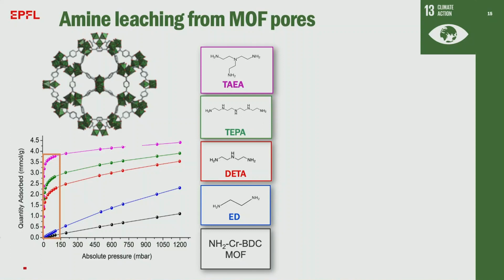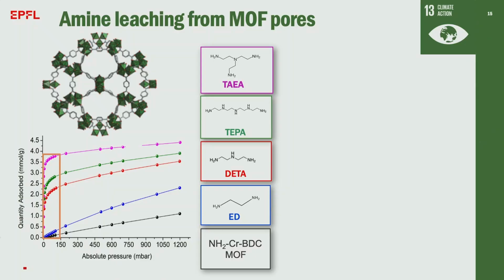So we began taking our metal organic frameworks and infusing them with amines, okay? Because amines interact very strongly with CO2, they're highly selective. So here in black, you can see the amount of CO2 adsorbed, okay, on the y-axis here. In black, you'll see our MOF unmodified, but you'll note as we add these different amines, all the way up to this amine here, TAEA, we significantly enhance the quantity of CO2 that we can adsorb in the material, okay? And it's because the amines inside are interacting with the CO2, okay?